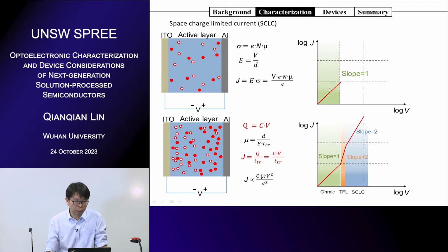At low bias voltage, the current, or the JV curve, follows Ohm's law. So it increases linearly with voltage. Everyone knows it from school. And if we increase the bias voltage, we can inject a lot of carriers. If the injected carrier density is much higher than the intrinsic carrier density within the active layer, then the carrier density changes. It immediately increases the conductivity of the active layer. That's why Ohm's law doesn't work for the high injection region, and we get the SCLC region.